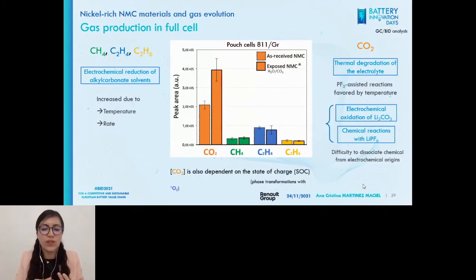So what we saw is that there are electrochemical reactions of the carbonates and also chemical reactions of the carbonates. We did several experiments to try to differentiate both, to see which is predominant, to tell the manufacturers which is worse, in fact, temperature or the first cycling. Unfortunately, we were not able to dissociate electrochemical from chemical reactions, but they exist.